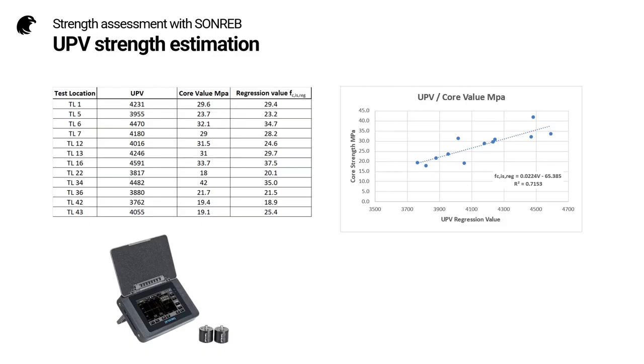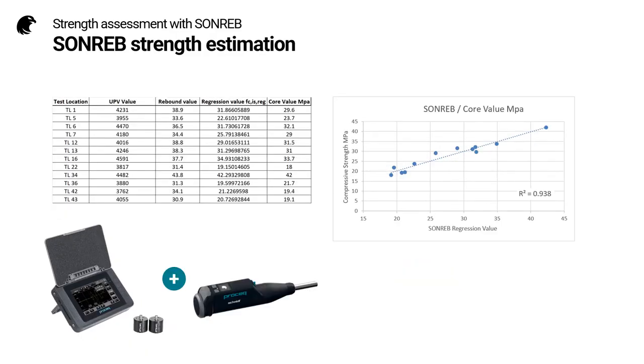Case 2 is to use the UPV regression, and in this case we have a 72% coefficient of determination. And finally, we will use the SONREB regression. And you can see in this case, we have a 94% coefficient of determination, which is a significant improvement on the estimate. And this is why people are drawn to use the SONREB method.